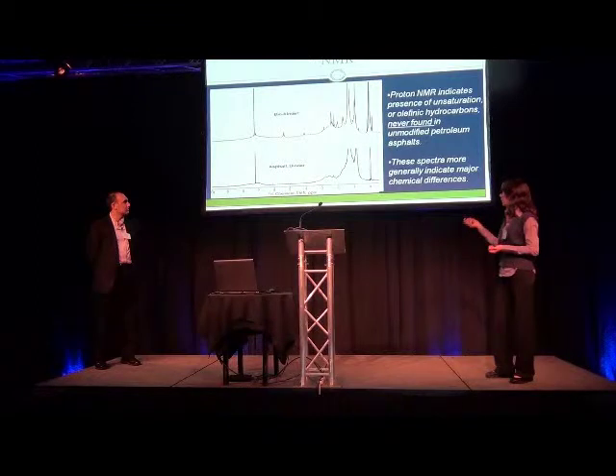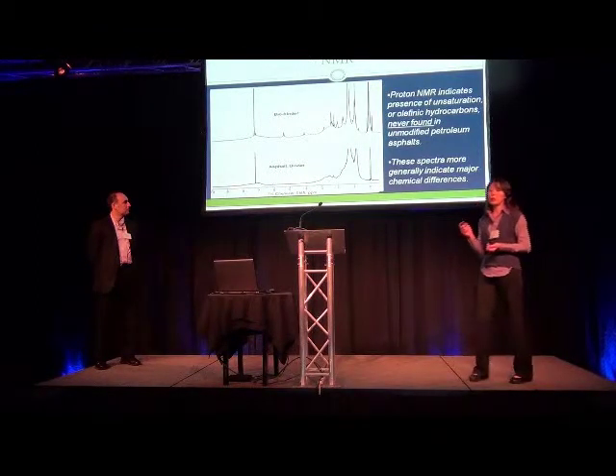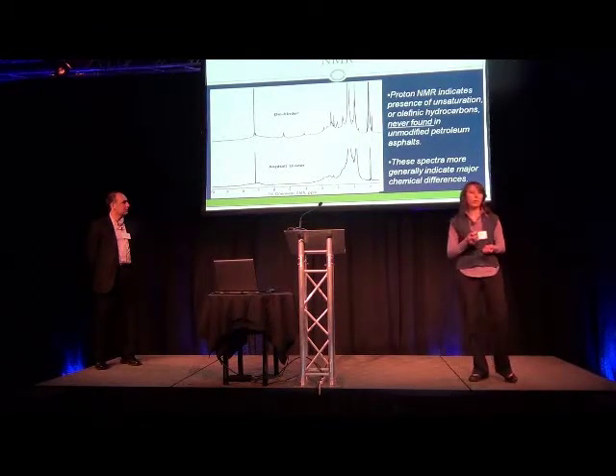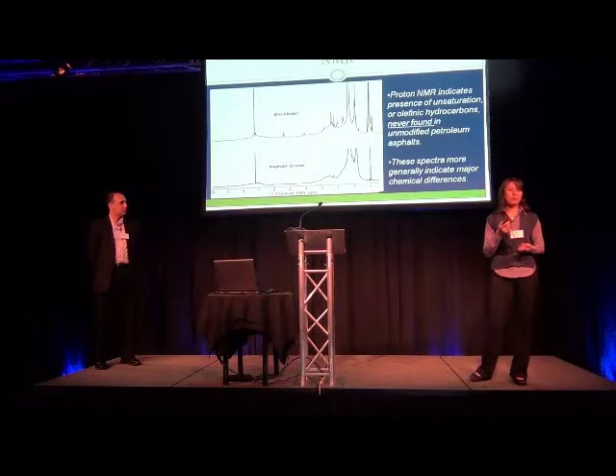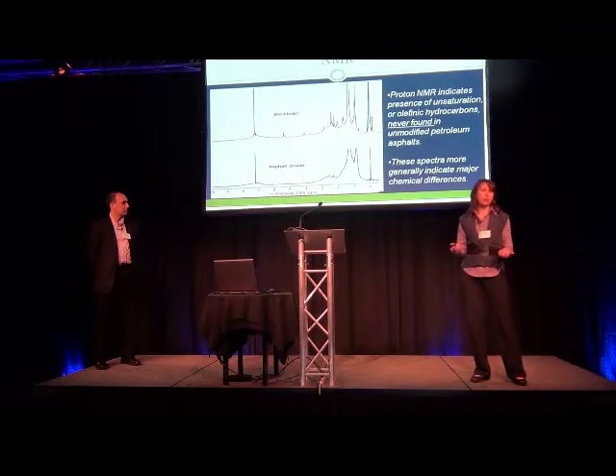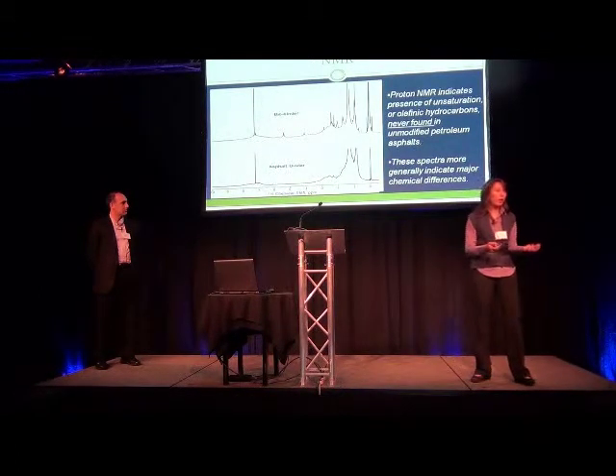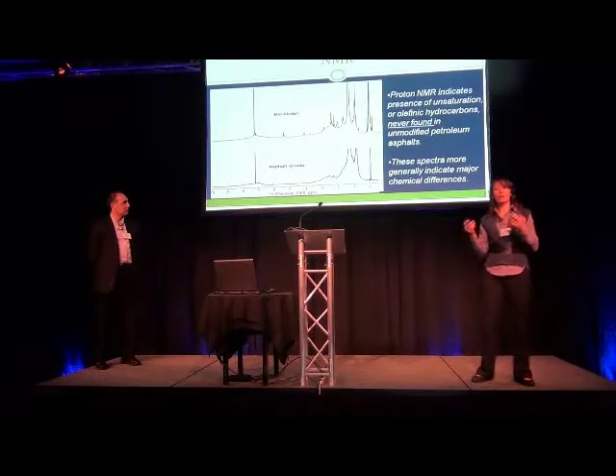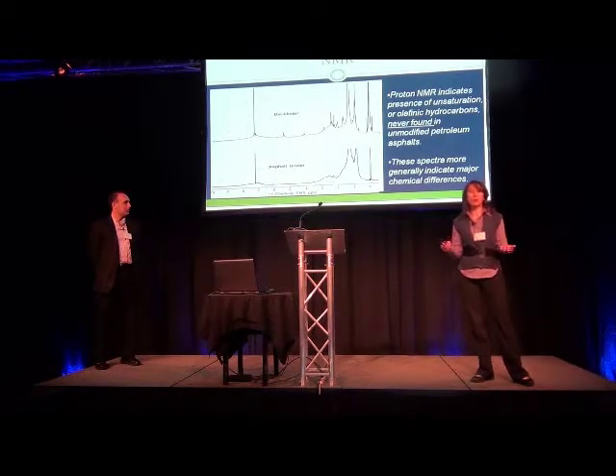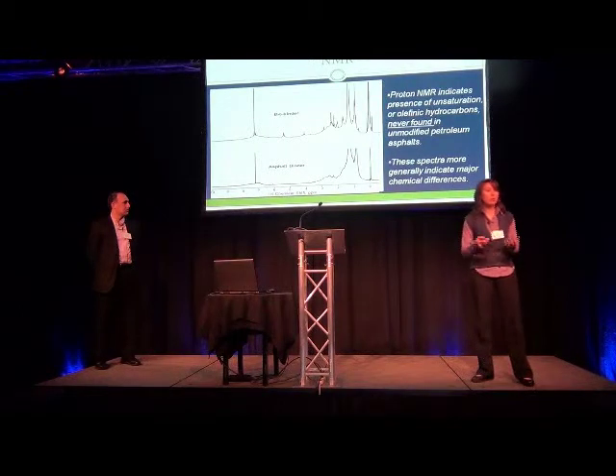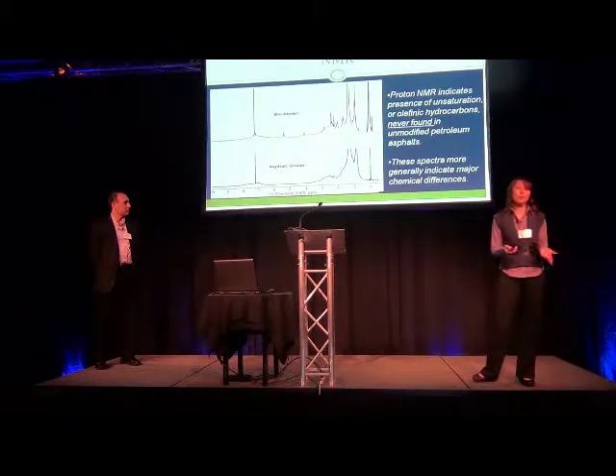So I don't want to go too detailed on the chemistry part, but we looked at the proton NMR, and we found that there are a lot of unsaturated olefins which we don't have in asphalt. But does it matter? In terms of the specification, it doesn't, because the spec that we have today is basically a set of mechanically driven tests. So you pass those tests, you're good to use it, and it performs the way you want it.